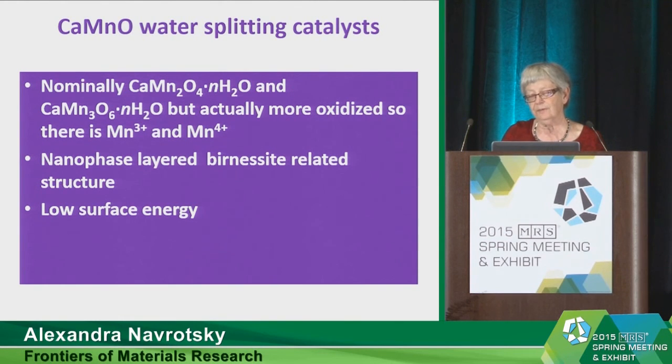What we found is there's a very good correlation between surface energy and the binding energy for water. That is, the higher the surface energy, the more tightly the water binds to the surface to essentially relax the surface. So, another criterion for excellent function for these materials, in addition to intermediate redox states, lower energy of oxidation reduction, a layered structure, easy accessibility, is a low surface energy, a surface energy that then enables one to easily move ions and molecules in and out. So that's beginning to be a prescription. Look for a good material. These are the properties you need to have.